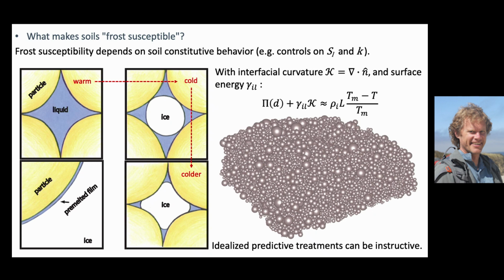If I make it colder still, that ice is able to grow, and it grows by invading the crevices in between adjacent particles. But importantly, this is a blow-up of some region around here, it maintains a thin liquid film that separates the particle from the ice. Okay, so this is the geometry that we expect. And with that interfacial curvature effect, so there's the Gibbs-Thompson effect here, and our pre-melting effect, so there's the disjoining pressure there, we can write an equation that describes the geometry of the interface as a function of temperature.